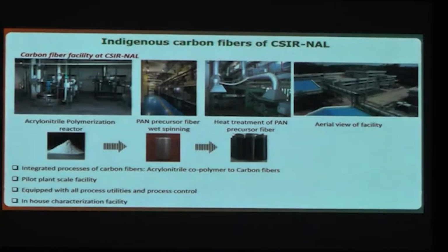Here in NAL, this is about the carbon fiber facility at NAL, and we have an integrated facility, basically starting from the starting material, acrylonitrile polymerization, to fiber to carbon fiber. It has basically three major processes. The first is the acrylonitrile polymer, where the suspension polymerization process is used, and the polymer is produced in a continuous reactor. We get a polymer powder from this reactor that will be dissolved, made into a solution, and spun through wet spinning technology.